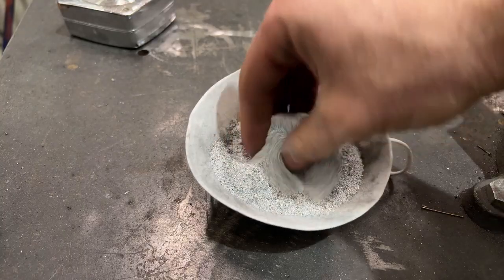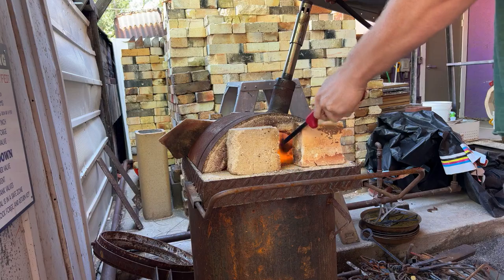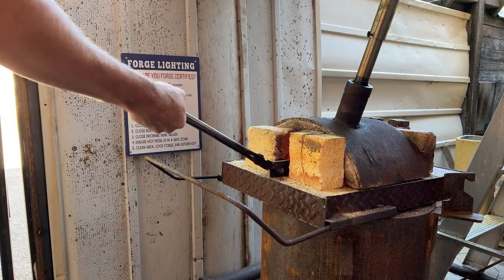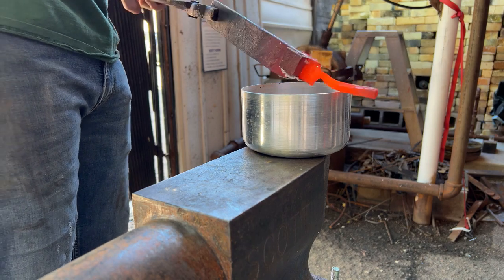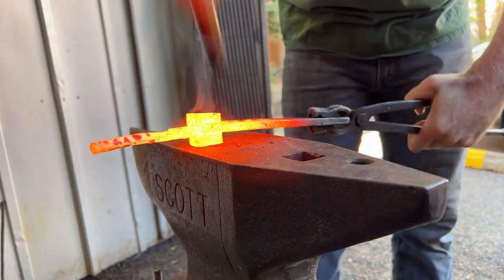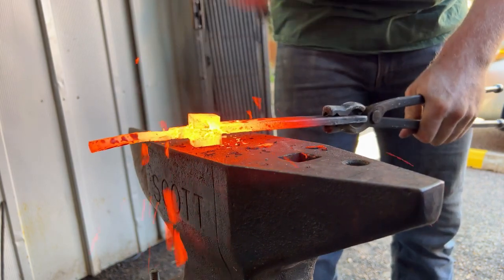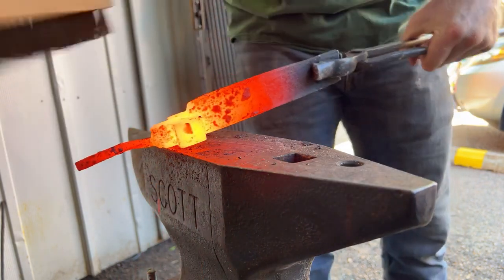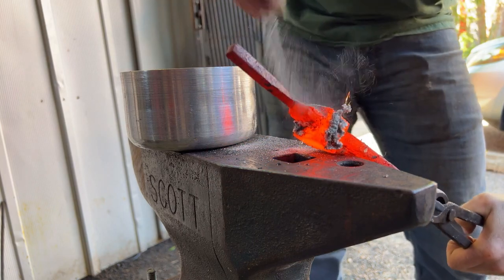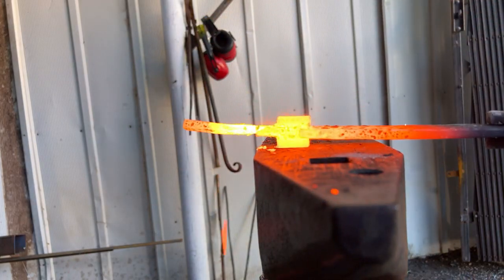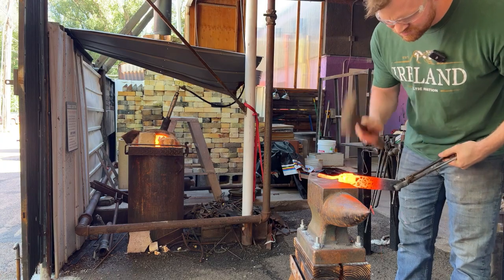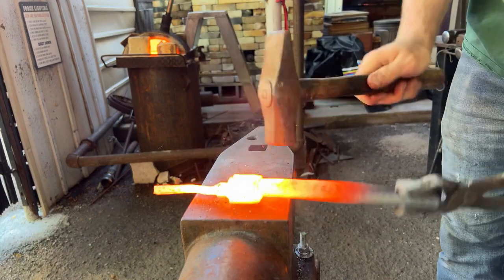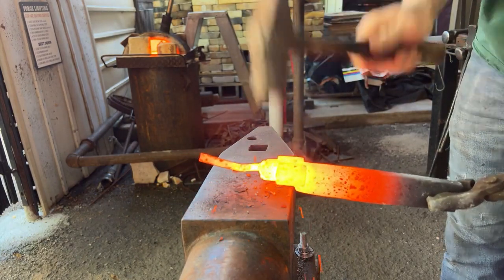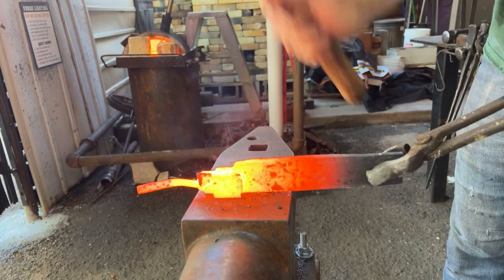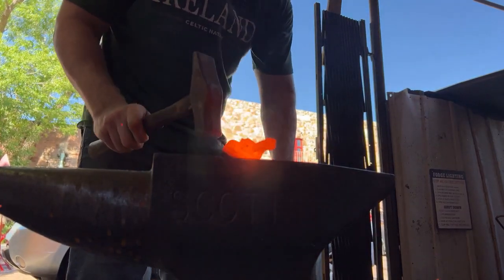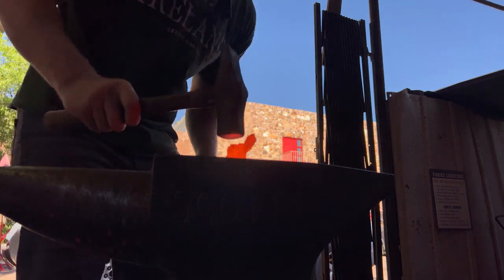Now, this powder that I'm saving is just dust from the wrought iron, and I mixed it into the flux, and it's going to be an aid in forge welding the bolsters on. I honestly just didn't think of it when I was welding the whole billet up together in the first or second day, but it was a really good thing I thought of it for this, because I'm not going to take as many welding heats for the bolster material. I don't want to forge it down very much at all. I just want to get it forge welded solid, and that's about it. And so those little iron filings, they melt in between the steel layers, and make the weld a lot easier and give me a little bit more confidence.